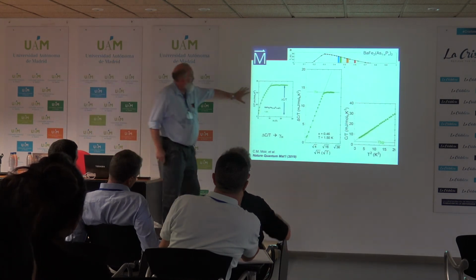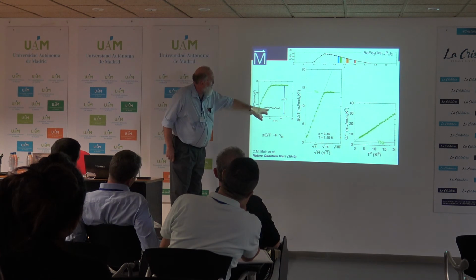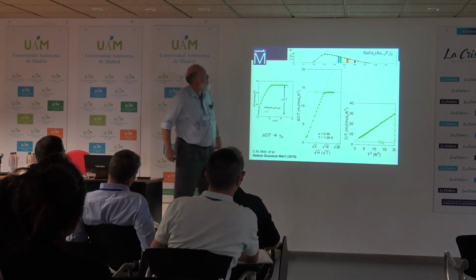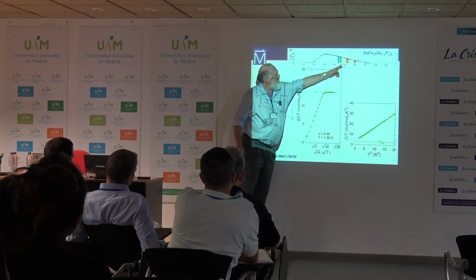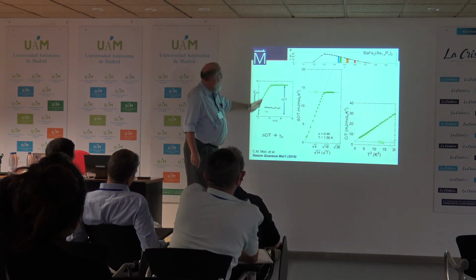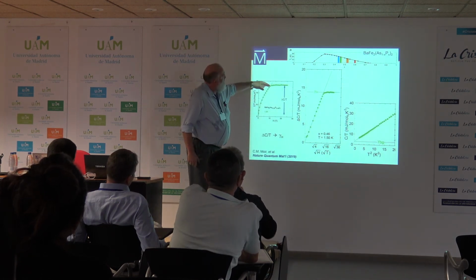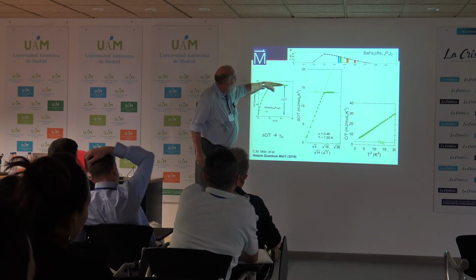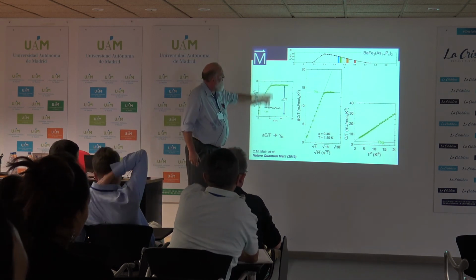Well, these are the data you've seen several times now on the sample with phosphorus doping of 0.46. So we're looking at this sample in green. And we've got a very clear square root of H, which evidences nodes in the energy gap, and then we get a saturation once we're above HC2.